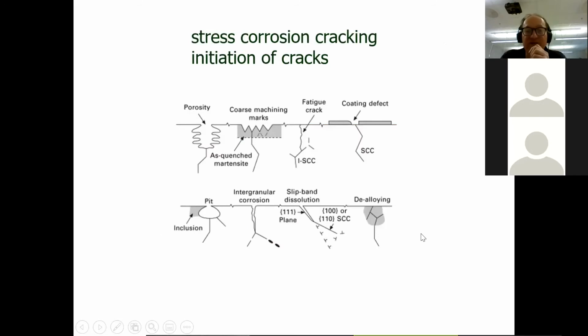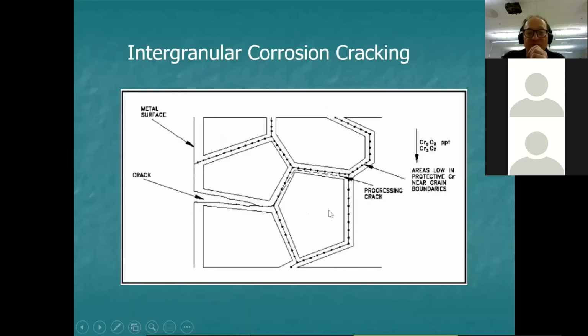And I've got some more diagrams here. I'm not going to go through all of them in any detail, but you can read this in your own right. It's just here for completeness. And we did this before in a previous lecture, so I'm just giving a link to that one where we looked at cracks and we looked at movement through the grains. This is intergranular crack propagation. And this happens to be in a weldment where we have a large amount of chromium carbide present. Remember what I said about chromium carbide in weldments? Well, that's also susceptible to stress corrosion cracking through intergranular cracking.